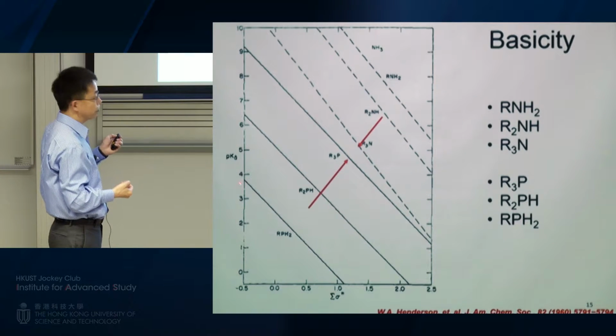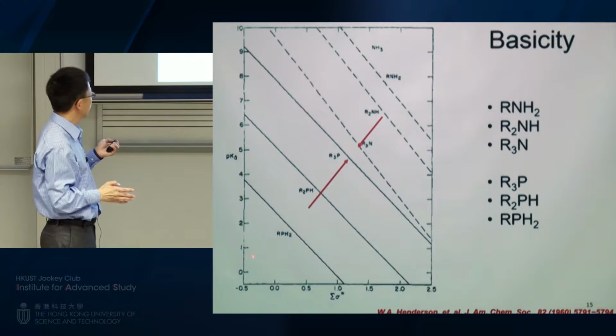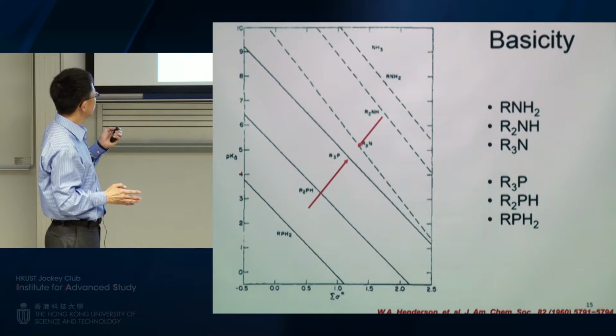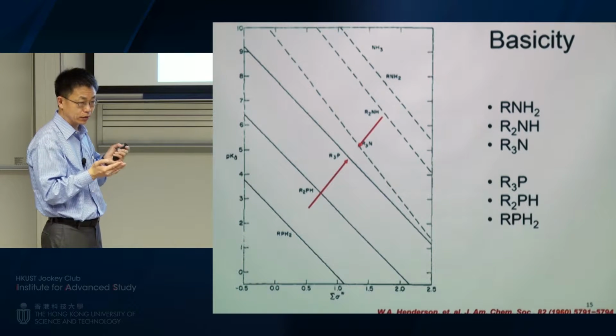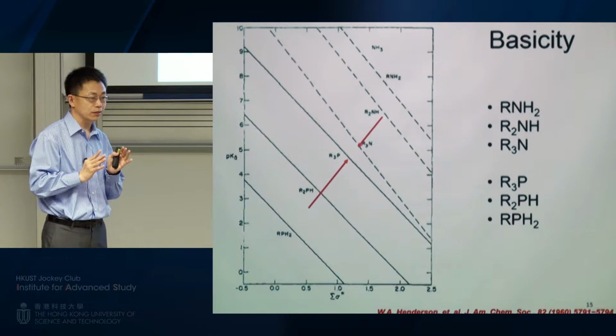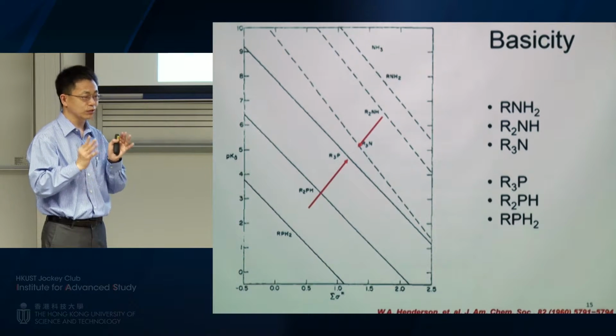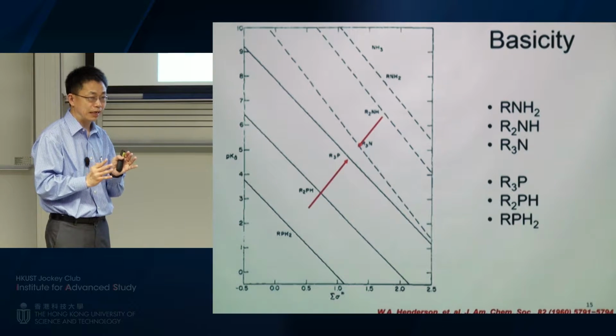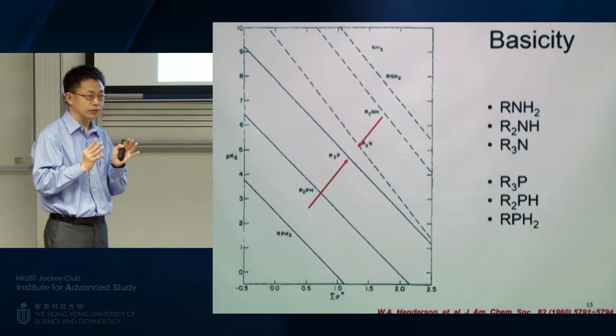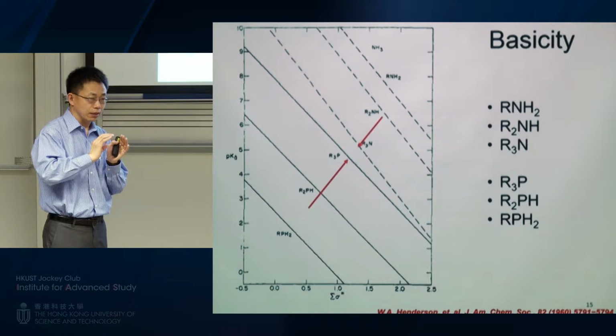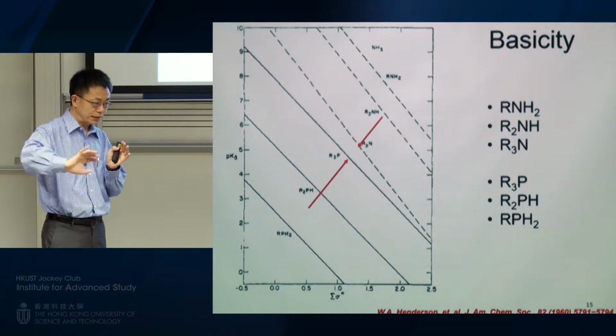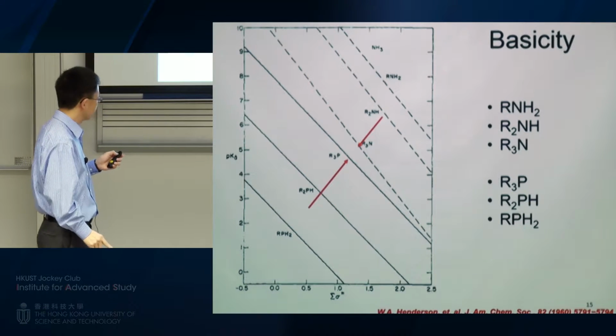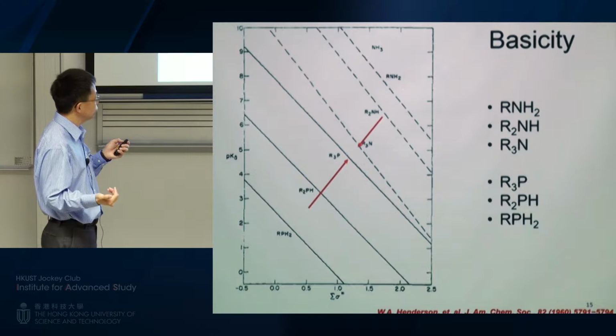The vertical axis is pKa. So simply translated, when you climb this axis, you actually get more and more basic. So in order to make a good hydroxide exchange membrane, you need higher basicity. And that's why KOH, potassium hydroxide, is the best hydroxide conductor. Unfortunately, we just don't want to use it. So you really need high basicity. Usually high basicity means the cation allows the anion to dissociate easier, to let go. And that's very important. So what we saw was really just intriguing.